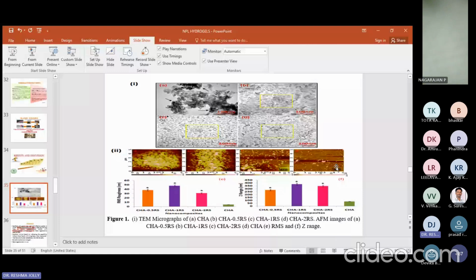So you can see when we are increasing the concentration of resin in the ternary system, the Z range is increasing. The RMS value is going to be around 40 or 50 nanometers. But the binary system is showing a significantly low value. So that was the advantage and that was the expected result.